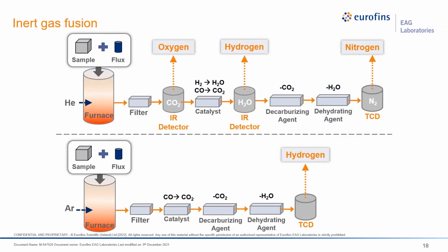This schematic shows a typical experimental setup to extract and detect oxygen, nitrogen, and hydrogen. As can be seen, after extraction, gases pass through a filter, mostly a particle filter, and are optimized in different ways before the analysis. During inert gas fusion using helium, first oxygen is measured, followed by hydrogen, and then nitrogen. The lower panel shows an example of using argon as a fusion gas and performing hydrogen analysis. As can be seen, hydrogen can be detected by both detection methods, infrared detectors and thermal conductivity detectors.